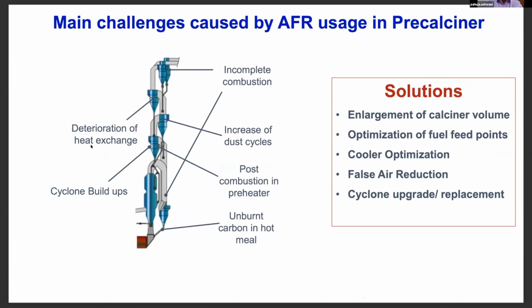And similarly, in the preheater and calciner, there are problems of incomplete combustion, deterioration of heat exchange because of the high amount of moisture, increased amount of waste gases or products of combustion, increase in dust cycles, post combustion taking place beyond the calciner because of the improper burning characteristics of the alternate fuels, and unburnt carbon falling into the kiln as hot meal. So these are the problems which are faced, because of which it creates a challenge for increasing the utilization, and the system design has to be proper for tackling all these problems. While there are solutions for these, at the same time it results in additional equipment to be installed at the plants, and a slight increase in heat consumption and slight reduction in the production of the kiln because of increased utilization of these alternate fuels.